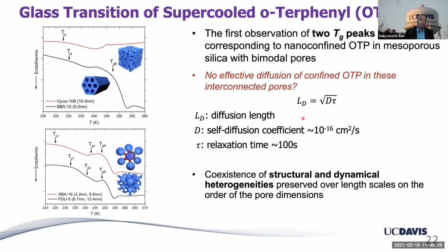But more interestingly, we were more interested in finding out the dynamical heterogeneity side of glass transition in these nano-confined spaces, whether there is a similar thing like we saw for melting of D2O. So here are data on OTP confined in these single pore sizes, and you can see the TG depression compared to the bulk TG, which is TG sub B. And you can see that there is one TG, but as soon as you put orthoterphenyl into these two-pore bicontinuous structures, again, mind you, these pores are continuous and interconnected, so OTP molecules have every opportunity to travel from one pore to the adjacent pore, which has a different diameter. Yet we see signatures of two glass transitions in these cases, as well as the bulk signal.